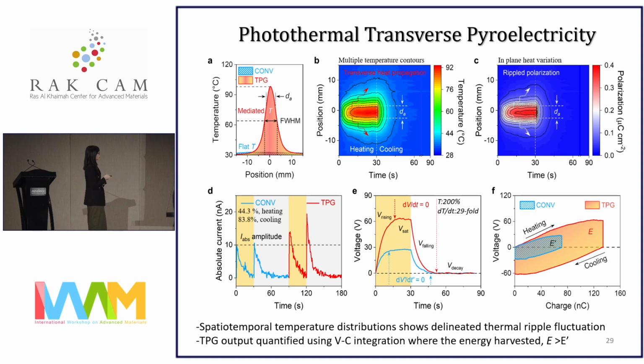In regards to the spatial temporal temperature distribution, we can see that the TPG during heating and cooling cycles has multiple temperature contours, which affirms that it has a delineated thermal ripple fluctuation. This originates from the photothermal hotspot in the center, and it propagates outward to the adjacent or peripheral area. Also, the pyroelectric coefficient has been used to quantify the polarization in the in-plane heat direction.